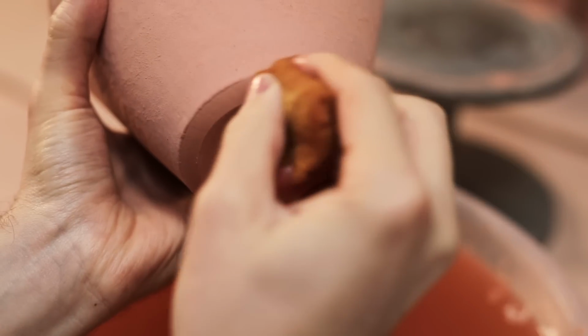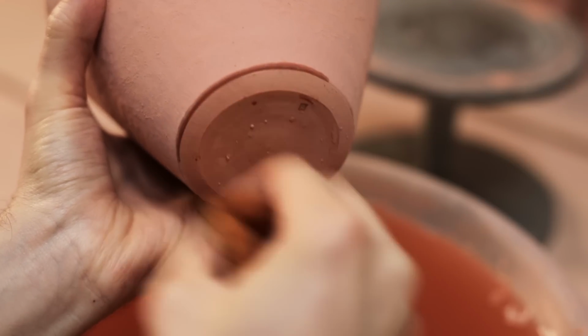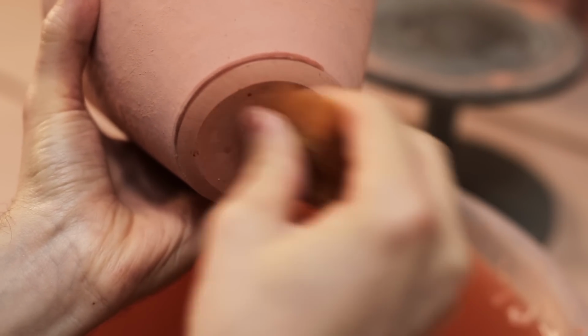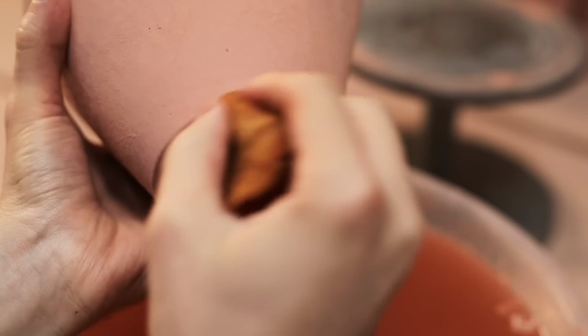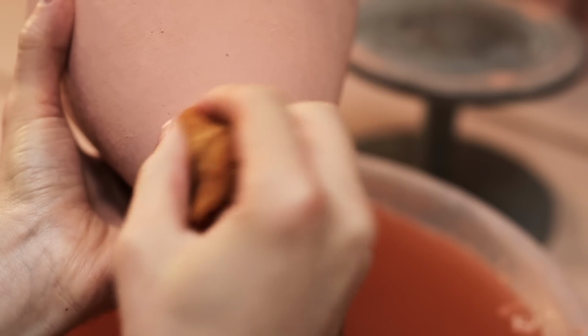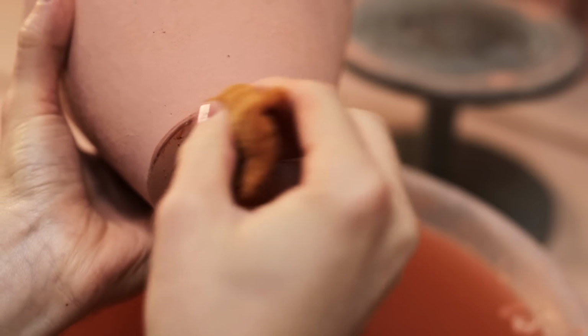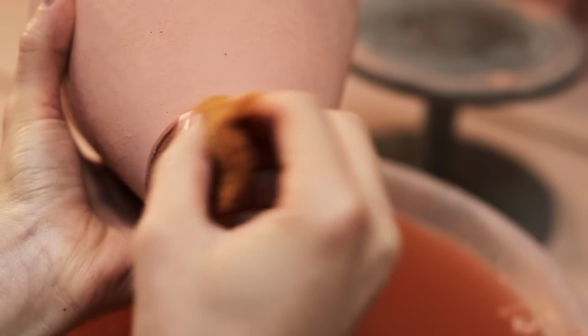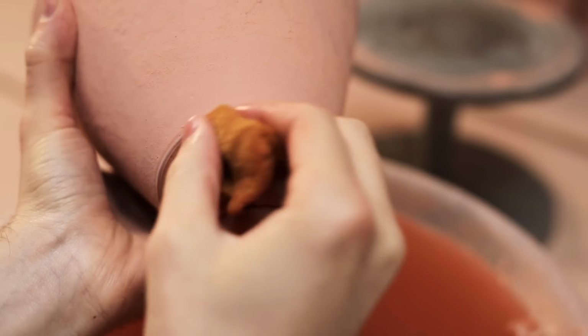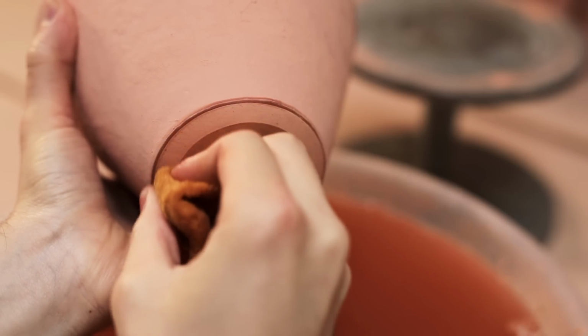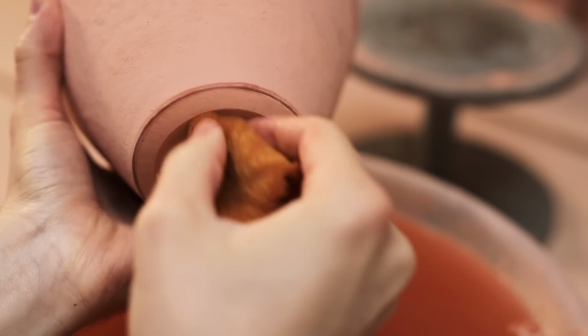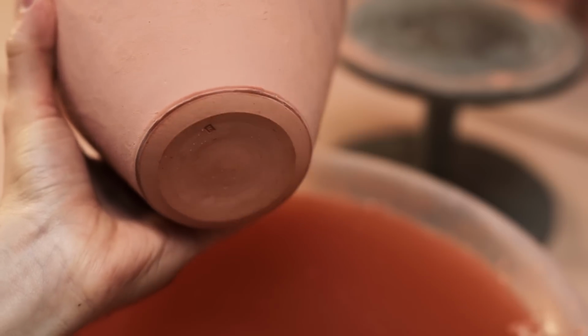The last section that needs to be tidied up is the base of the pot itself. Here, I need to make sure that I remove any speck of glaze from the bottom, as all it takes is one tiny drop to fuse the pot to the kiln shelf, which could be enough to damage the pot. I also make sure that the line between glaze and clay is as clean as it can be. I don't want it to waver or be uneven. Instead, I want it to be neat and straight all the way around.